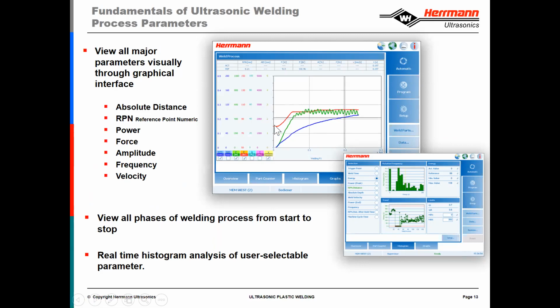So you can see in the red curve here, we triggered at a point at about 80 pounds of force. We profiled up to about 100 pounds of force for the initial weld stage. And then you can see here, the weld profile increased slightly, and then it increased slightly again. So we have weld force 1, weld force 2, weld force 3. And again, this joining velocity curve is pretty good.